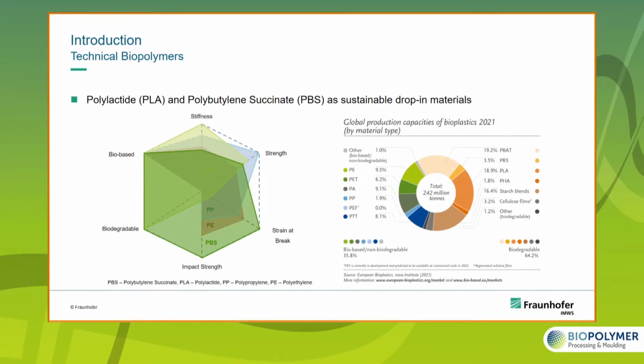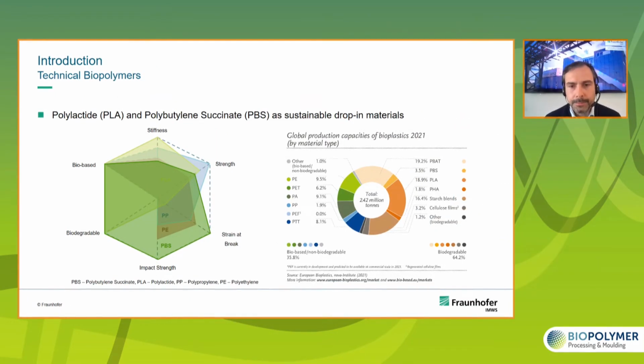Here are recent market data for those bio-based and biodegradable polymers. And you can see that especially for PLA and PBS, the shares are increasing, and PLA actually has a share of 18.9% of the global biopolymer market within the range of the biodegradable materials. PBS just has 3.5%, but this share in the future will strongly increase. And as mentioned, those two materials are very interesting for replacing polyethylene and polypropylene.